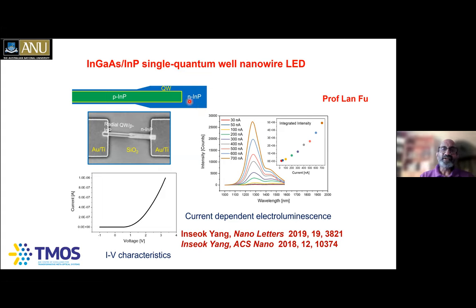So now you can see that this is a schematic of the structure which he was aiming for, and his actual device is a structure which he was able to grow, which took about 2 years to optimize various structures in order to get good quality nanostructures and quantum well. Then he transferred them onto a glass slide and made contacts using electron beam lithography, putting some metal contacts so that he can inject current into these ones.